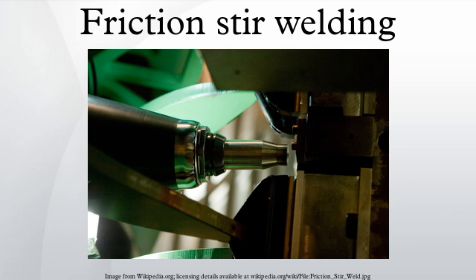Hot work tool steel such as AISI-H13 has proven perfectly acceptable for welding aluminium alloys within thickness ranges of 0.5 to 50 mm, but more advanced tool materials are necessary for more demanding applications such as highly abrasive metal matrix composites or higher melting point materials such as steel or titanium. Improvements in tool design have been shown to cause substantial improvements in productivity and quality.